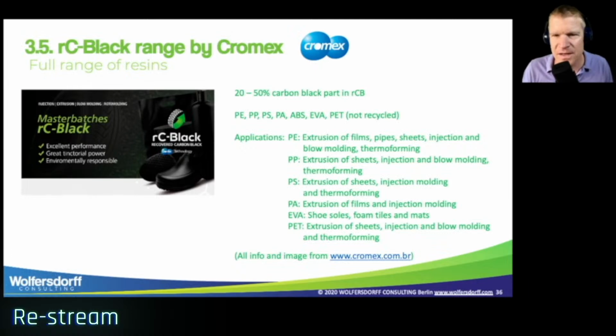So Cromex specify not the total RCB content, but specify the carbon black part in the master batch. So the total recovered carbon black content is way above 20 to 50%. What I like also is it's almost a complete range in terms of the resins. It's polyethylene, polypropylene, styrene, polyamide, ABS, EVA, and PET, also called polyester.